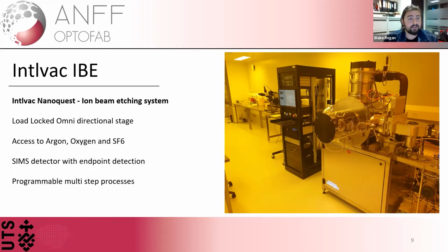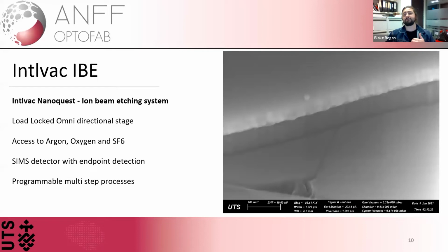A good example of that is the use of oxygen, which is used for diamond. These are some of our first tests where we were just testing with a basic SiO2 mask on a diamond substrate. And we can see that with this use of an oxygen etching mechanism, we can have nearly pristine etching of the diamond surface and a near direct translation of the SiO2 mask onto the sidewall. Unfortunately, in this case, the mask itself was a bit of a rush job, so it's not as pristine as we can make it. But it does show a nice translation of roughness of the mask directly into roughness on the sidewall, which then also shows that the etching mechanism has very little effect on the SiO2 and a lot of effect on the diamond substrate. So that was a nice little demonstration of the selectivity that can be granted through chemical etching.